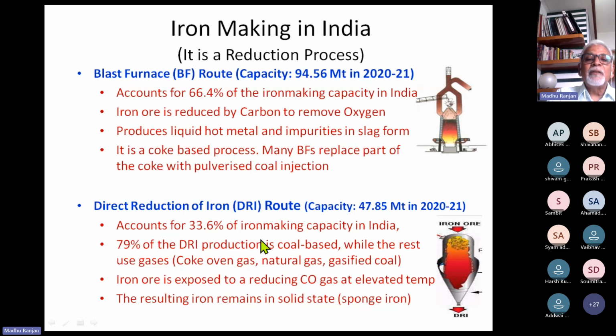The other method of producing iron is the direct reduced iron or sponge iron, as we commonly say. They constitute about 1/3 of the entire iron that is made in India. Out of 47.85 million tons of DRI which was produced in 2021, about 79% were produced through coal based DRI, while the rest, 21%, were produced using gases. The gases could be coke oven gas, natural gas, or gasified coal.